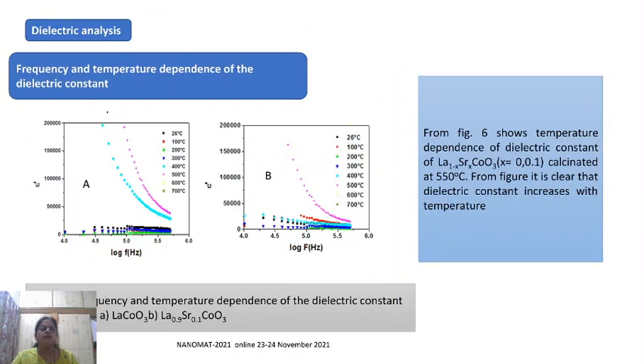Dielectric analysis. To study the electrical properties, we have performed the dielectric analysis. Now, in the dielectric analysis, we have studied the frequency and temperature dependence of the dielectric constant. Figure A shows the frequency and temperature dependence of the dielectric constant of the pristine LaCoO3. From this figure, you can see that the dielectric constant increases with temperature, while figure B shows the Sr substituted LaCoO3. Here also you can see that the dielectric constant increases with temperature.